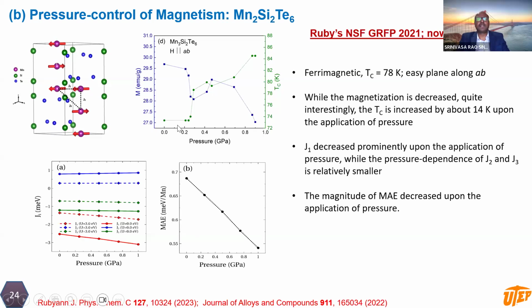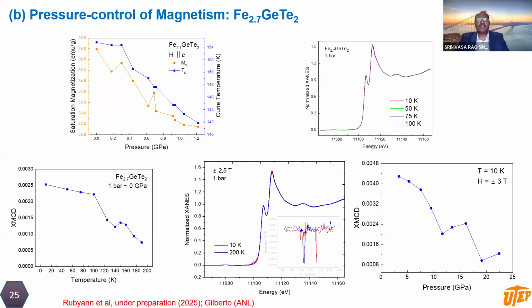And this work was cited by other groups, from other campuses, and they have gone up to about 20, 30 gigapascal, and they were able to increase the Curie temperature further. That motivated us to go for much higher pressures on another independent compound. For example, take a look at this compound, iron germanium telluride. This is one of the compounds that people study heavily because it shows relatively very high Curie temperatures, from above 150 Kelvin until 300 Kelvin, just by changing the iron vacancies. So that's why this compound is interesting.